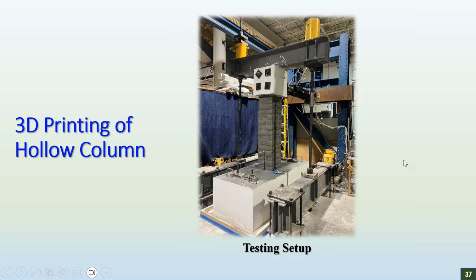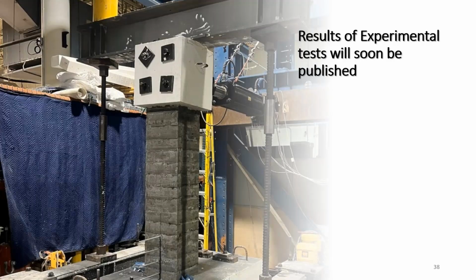So this figure shows the testing setup for this 3D printed hollow UHPC column, and the axial load was applied by using the hydraulic jacks on top, and the lateral load was applied by using a 150 kip servo actuator on the side. The results of this experimental test will be published soon. The next part will be presented by Dr. Azizinamini.